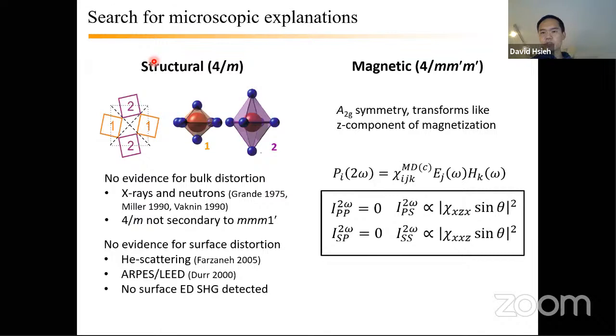And so the simplest magnetic point group we can consider is 4/m, m', m', where these vertical mirrors, corresponding to the last two m's, are broken by virtue of some magnetic order. The prime is just time reversal, so m is not a symmetry, m' is a symmetry. Now, when you go from 4/mmm to 4/m, m', m', you have some magnetic order that transforms like the A2g irrep of the high temperature point group, and this transforms like a z component of magnetization. So if you had ferromagnetism, that would satisfy this magnetic point group, for example.